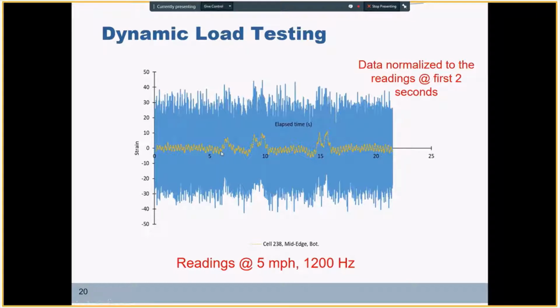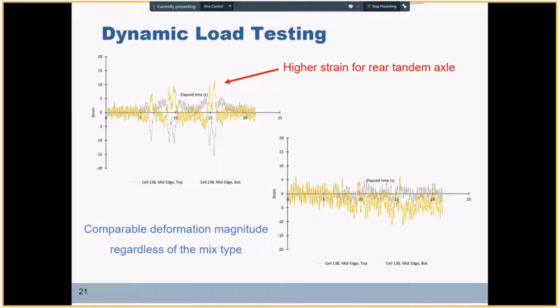Here we can see and trace the 5 axles of the truck. The average deformation values at 5 miles per hour for these 2 sections are less than about 10 or 15 microstrain, in compression or tensile direction, for both sections. Again, comparable behavior for the 2 test cells, comparable deformation magnitude, and in most places comparable deflection patterns as well, regardless of the mix type.